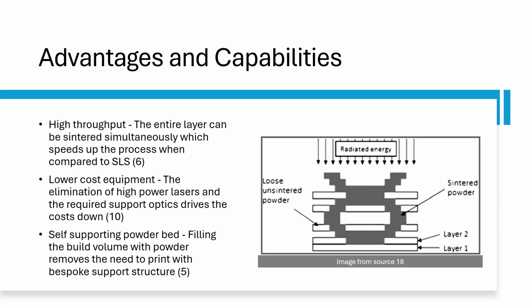High-speed sintering has some distinct advantages over the processes it is competing with. Because each layer is fused in a single pass, throughput is much higher than selective laser sintering and can be as much as 10 times higher. And while the processes are similar, high-speed sintering also beats multi-jet fusion in terms of volume printed per hour. Eliminating lasers and optics used in selective laser sintering also cuts equipment cost. And since the surrounding powder supports the part, there's no need for custom support structures, which simplifies post-processing requirements.